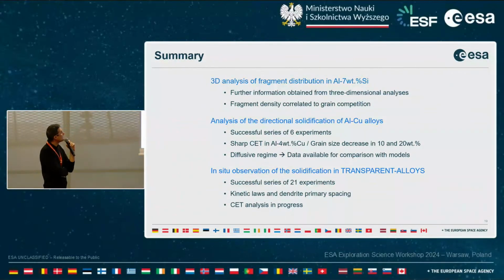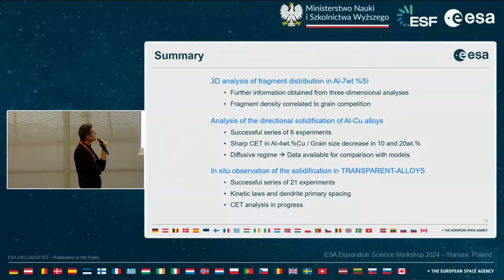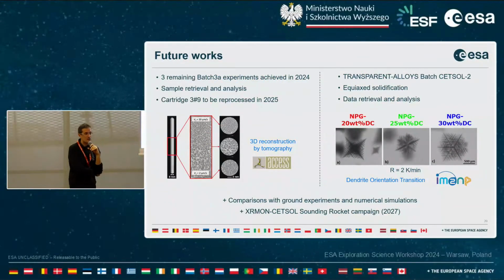So to summarize, we carried out advanced characterization in 3D of aluminum silicon samples. We also studied aluminum copper during batch 3A and reached a diffusive regime, so data is now available for comparisons with models. In situ observation of solidification in transparent alloys was also successful. And the CET analysis in this experiment is still in progress. And what are our future works? Well, it will be mainly focused on two last experiments.